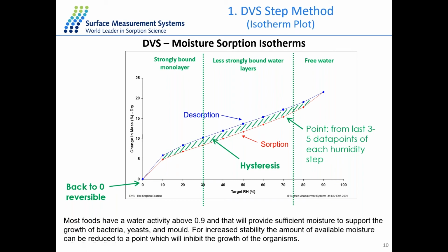So for example, if there is more energy input, like a higher temperature, if you perform the same experiment, there will be more energy for the water molecules for diffusion. Then you will be expecting a smaller or narrower hysteresis gap compared to 25 degrees, this one. I do have an example later with the microcrystalline cellulose that I can show you how the temperature will affect the hysteresis gap.